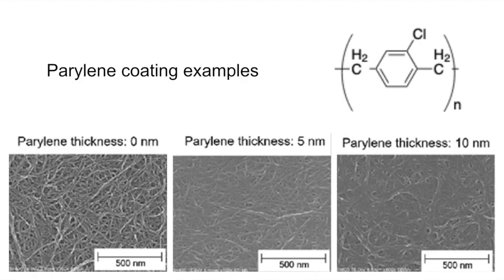of Parylene. So the first picture on the left shows a material without any coating, and then the middle one has 5 nanometers of the Parylene coating, and the one on the right has a 10 nanometer coating. And if you zoom in, you can see that the porosity significantly decreases as the coating thickens.